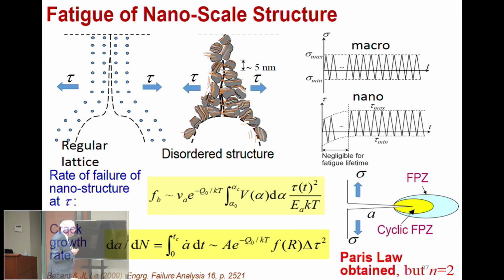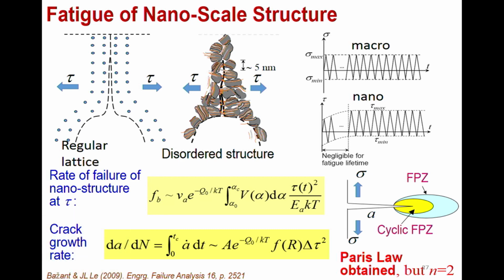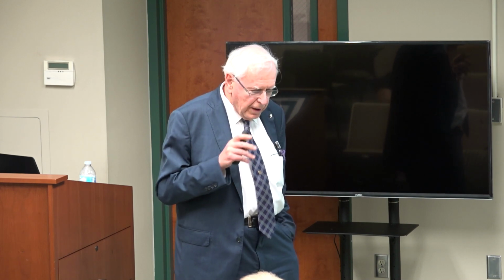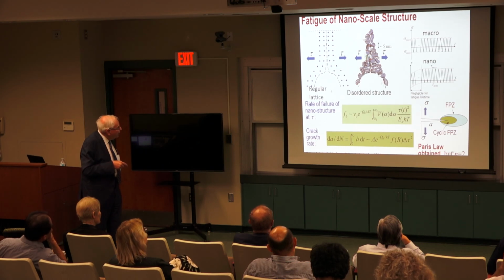The theory has been extended to cyclic and static fatigue. Now then you have another case. You need to realize that for lifetime, with fatigue until failure, the crack grows, but grows subcritically. So it's not a question of the tail in the mean. And we have a well-known law, Paris law for cyclic loading, or Charles-Evans law for static fatigue. So you can again imagine in concrete it looks like this. There are nanoscale particles, but no order as in crystal material like this.